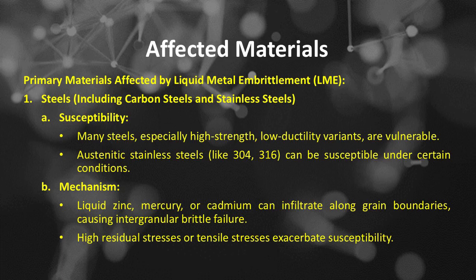Steel susceptibility: many steels, especially high-strength, low-ductility variants, are vulnerable. Austenitic stainless steels, like 304 and 316, can be susceptible under certain conditions. The mechanism of liquid metal embrittlement in steel materials includes: liquid zinc, mercury, or cadmium can infiltrate along grain boundaries, causing intergranular brittle failure. High residual stresses or tensile stresses exacerbate susceptibility.